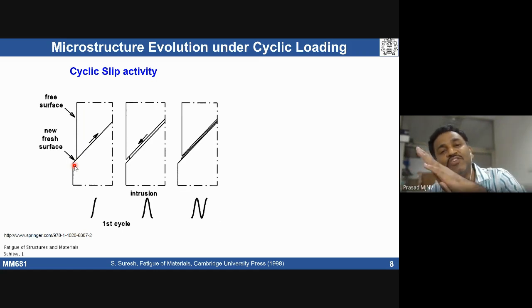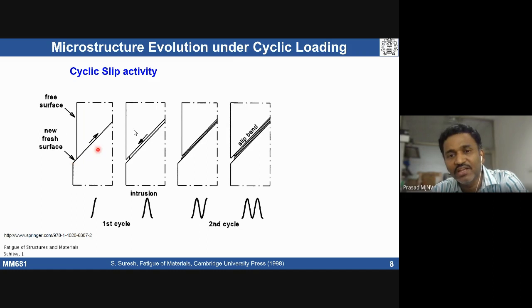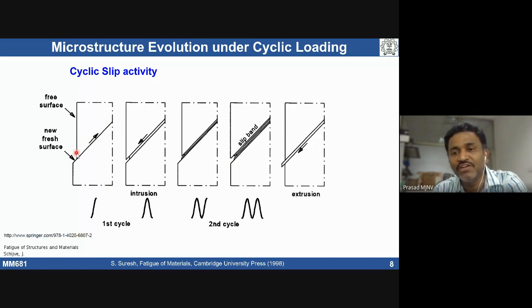So this slip activity is what we are talking about as cyclic activity. We are changing the stress, high to low, low to high. So that can lead to local slip activity, and we are going to see formation of slip bands. Near the surface, some kind of intrusion is going to form in the material if the initial slip activity happens in this direction. If the slip activity happens in the other direction initially, I'm going to see an extrusion kind of defect.